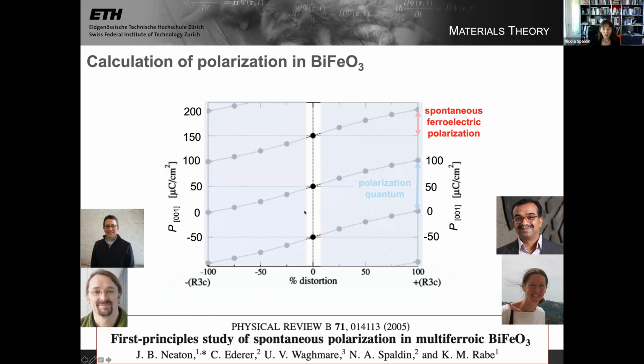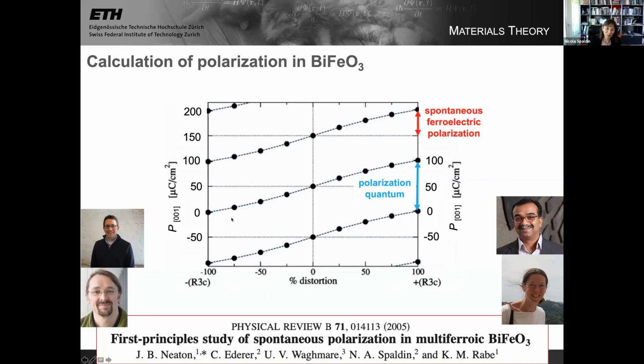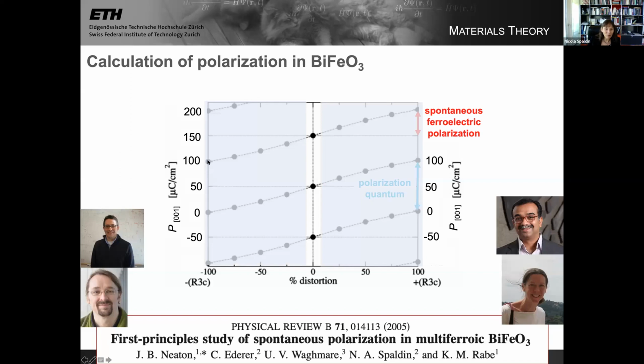And first I want us to look at the undistorted, centrosymmetric, non-polar structure and look at the values that one calculates for the polarization. I have to confess, I think this was done using the VASP code. I'm sorry, it was a long time ago, I don't remember. But let's look at the values. For the non-polar, non-distorted structure, we see that we don't have 0 as a polarization. We have 50, minus 50, 150, minus 150, and so on. So this is exactly analogous to the simple one-dimensional chain that we looked at. The undistorted centrosymmetric structure has a polarization lattice that doesn't contain 0. It contains instead the half polarization quantum, which turns out to be 50 microcoulombs per square centimeter in this case.